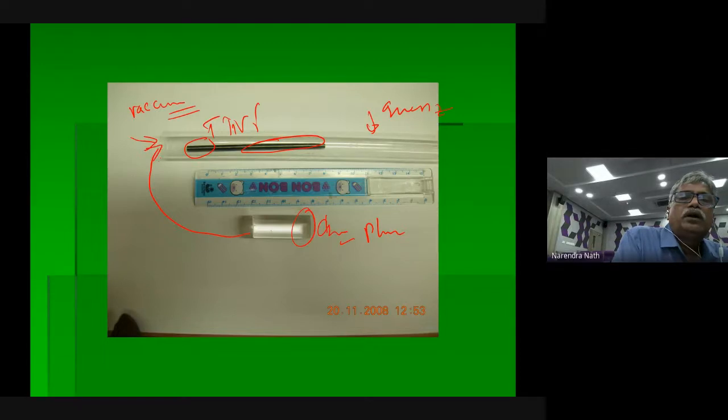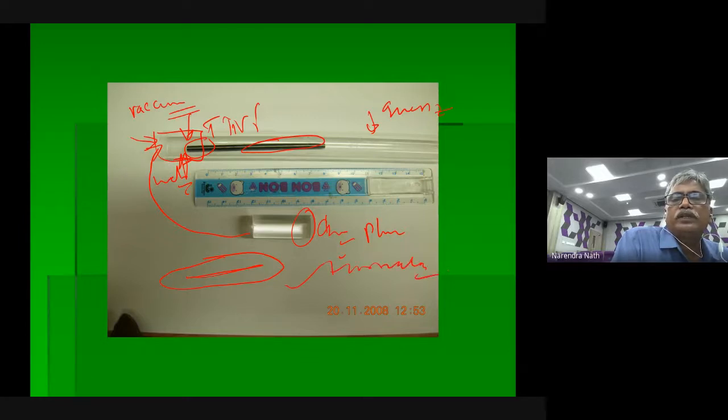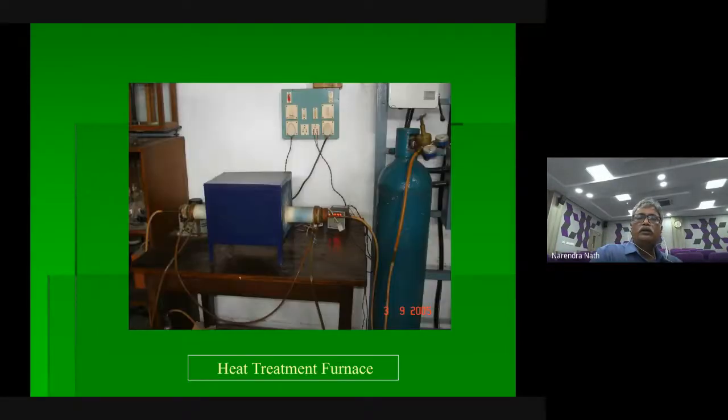After placing this, you are going to seal it, with the kind of glass welding they make. Then it becomes one tube, both ends closed. Inside there is a titanium nickel rod. Okay. So this you can put in the furnace to get clarity in it. This is what people do if you have the facility.